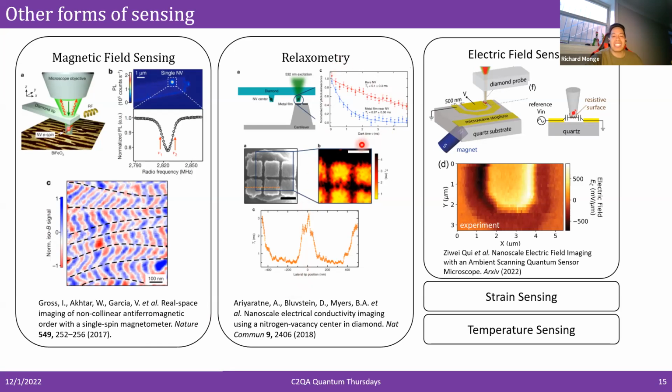They scan the NV center and perform T1 relaxation measurements on that NV center, and then from the T1 obtain the conductivity of that nearby metal film. So you can see they also mapped out these nano patterned metal films in here. So that's really nice application.